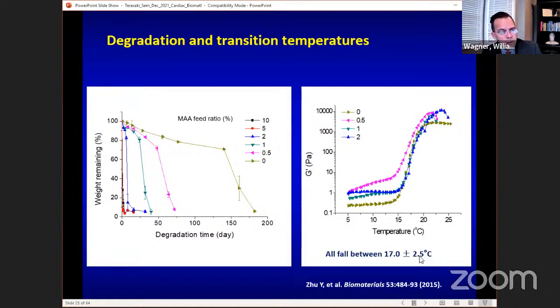They're all plus or minus 2.5 degrees Celsius in terms of their phase change, but they have radically different degradation times. So with low methacrylic acid or 0, you can see the degradation time is way out here. And with high, it's very quick, a day or so. So we can tune by changing those molar ratios. We can do like we did with a polymer with ester and carbonate. We can change the rate of degradation.